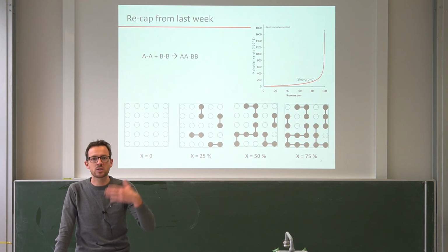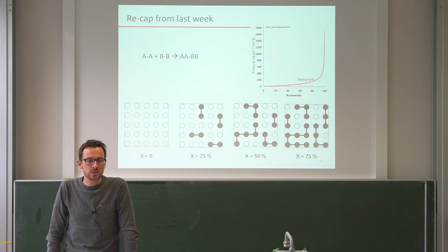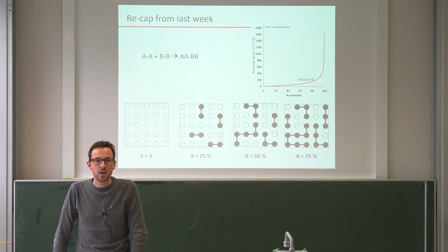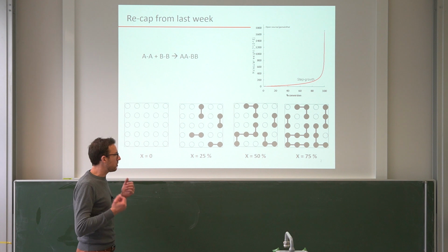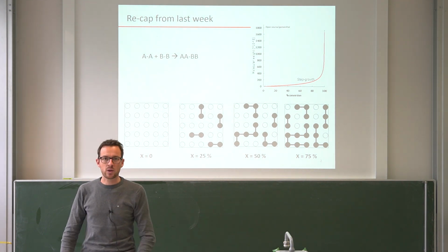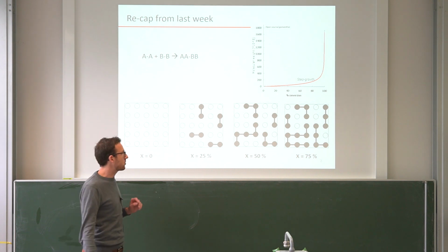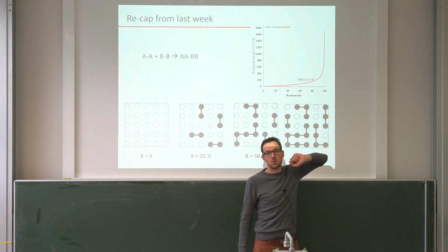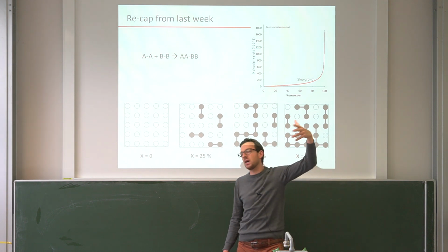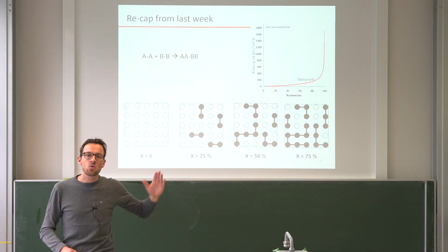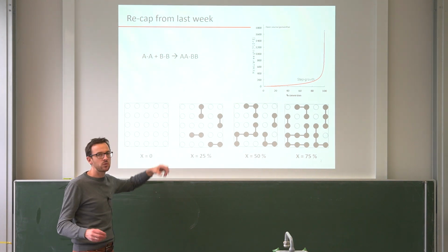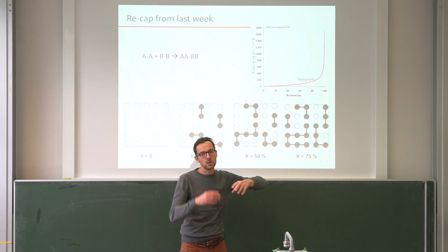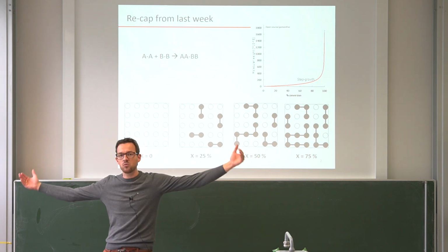We made a couple of examples, for example, polyesters, polyamides, polyurethanes, and then we looked into the theory on how to describe such a reaction. This is known as the Carothers theory, or based on Carothers equation. And what is essentially predicted is that in order to control such a reaction or to make polymers by such a reaction, we need to run it to very high conversions. So this is what you see here. Only if the conversion, so the extent of the reaction, approaches very high values, 99%, 99.9%, and so on, do we get large polymers. And this is a direct consequence of this step-by-step addition of monomers. Now you see, even if we link things, it takes a long time until these longer and longer chains actually connect and then form really long chains.